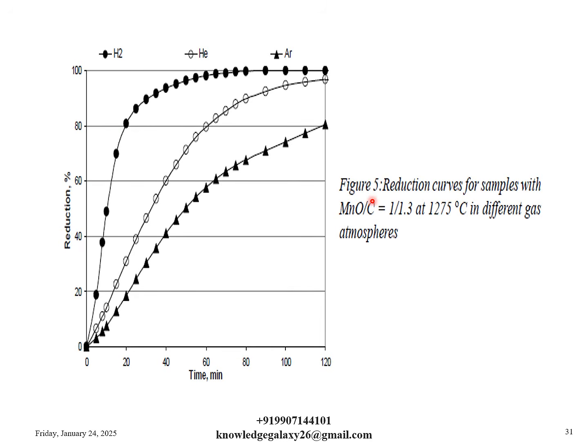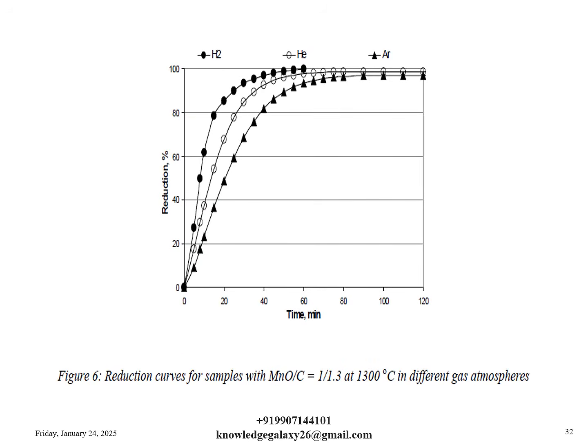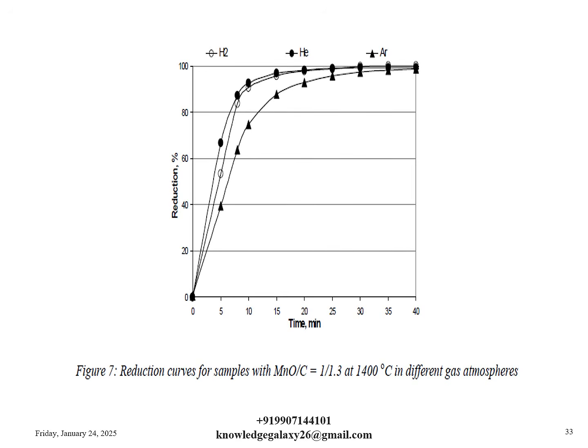So this is figure 5, which shows the reduction curves for samples with MnO by C ratio equal to 1 by 1.3 at 1275 degrees Celsius in different gas atmospheres. And this is figure 6, which shows reduction curves for samples with MnO by C ratios equal to 1 by 1.3 at 1300 degrees Celsius in different gas atmospheres. And this is figure 7, which shows reduction curves for samples with MnO by C ratios 1 by 1.3 at 1400 degrees Celsius in different gas atmospheres. I have just described all three curves, so please recall that.